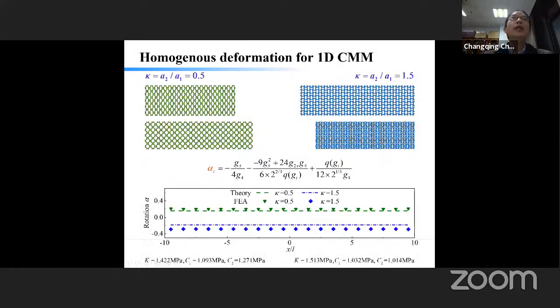So for the two examples we showed before, we showed the finite element simulated results for kappa equal to 0.5 and kappa equal to 1.5. We show the rotation for each unit cell. You can see the dash-dot line actually agrees with the theoretical model. So here is the finite element, and here are the theoretical results. You can see they agree with each other quite well. So basically, the 1D chain model can predict the finite element deformation.